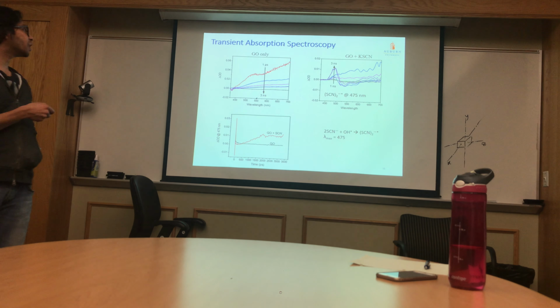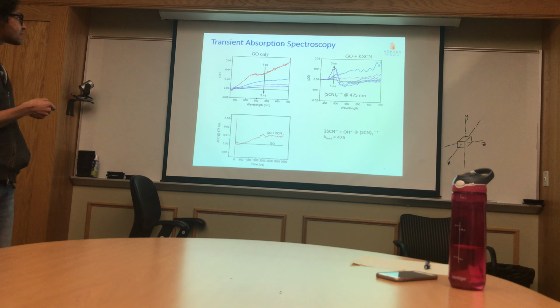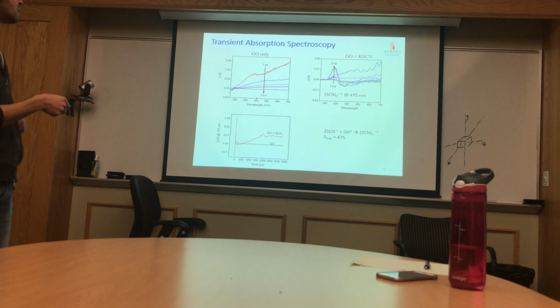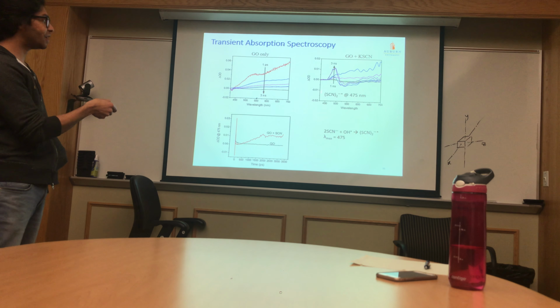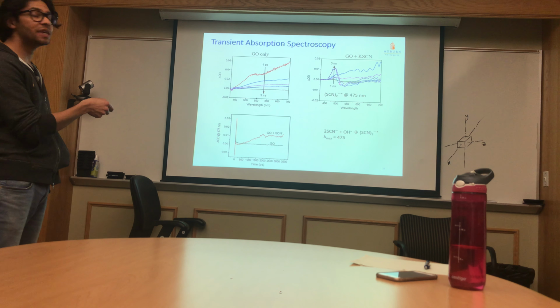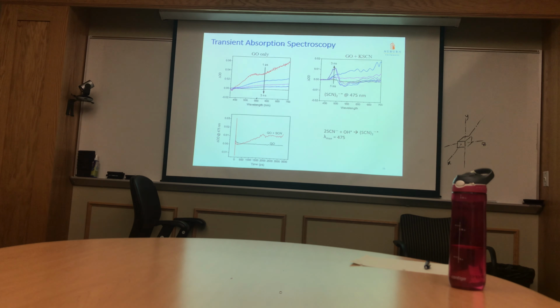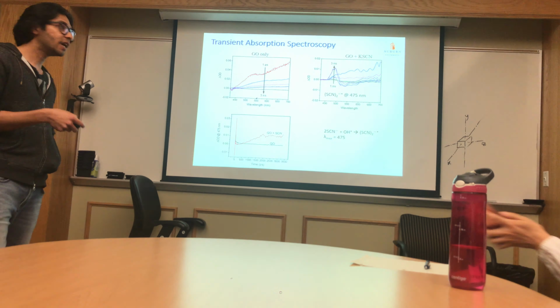So we did our experiment where we used graphene oxide, and in another sample we used graphene oxide plus KSCN. Now KSCN is a probe molecule. If OH free radical is produced, it forms this radical, and it has a unique transient absorption peak at 475 nanometers, which agrees well with the literature. When we added KSCN, we actually saw a peak evolving. That means from this we were able to prove that OH free radicals are again formed, and we are also able to see the evolution time of the OH free radical. I have to prepare more on this side.